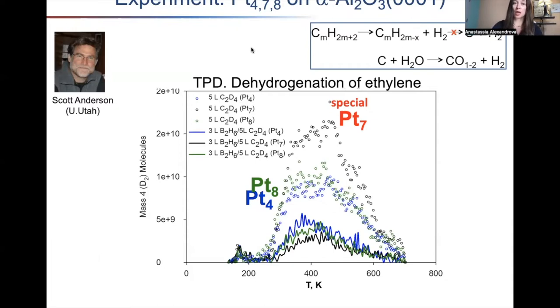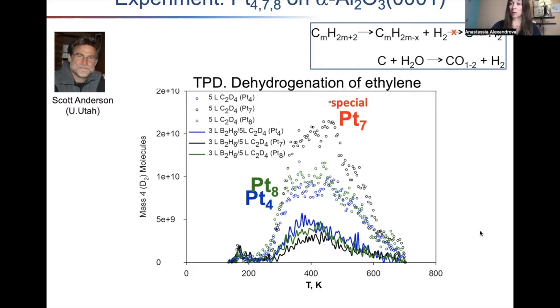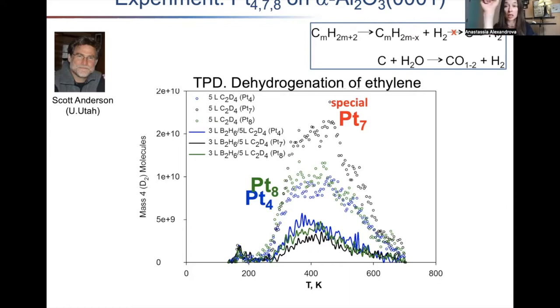Here is a very fundamental question: we looked at the performance of size-selected platinum clusters of sizes four, seven, and eight supported on alpha-alumina, catalyzing dehydrogenation. We took ethylene as a proxy for the olefin intermediate we'd like to desorb rather than dehydrogenate further. Starting from an alkane would be ideal but Scott doesn't have a high-pressure reactor in combination with all other capabilities. Looking at this intermediate makes more sense since that's where the bifurcation point in the mechanism really is.